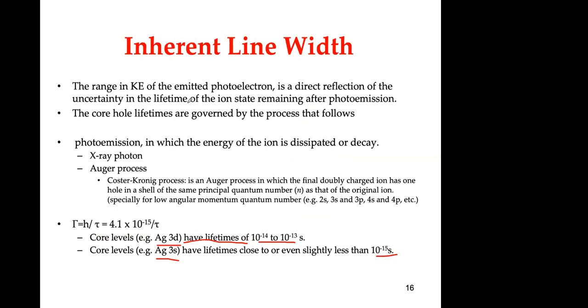And the other: when you do the photoemission, the photoelectrons coming out, you will have X-ray fluorescence and Auger, and this might also affect the delta E a little bit. Remember in Auger, you have an element that is zero, then you remove one electron and it's positive one, and then if you do an Auger transition, you get a second charge. So it's highly charged actually. This affects the kinetic energy of the electrons coming out as well. So those are parameters that are inherent in the delta E.